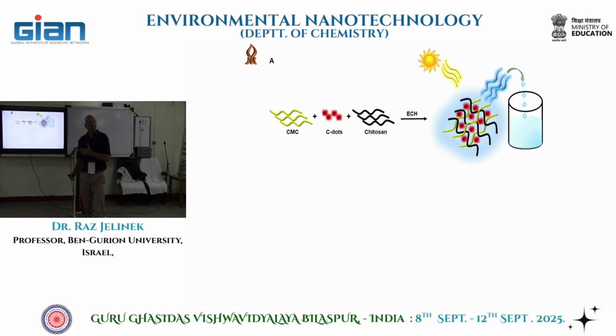Let me describe the system that we made in our lab for water purification or water desalination. What we did, we took carbon dots and mixed them with two very cheap polymers. One is called chitosan, actually a very simple polymer that you can also find in plants. And this is CMC, carboxymethylcellulose.